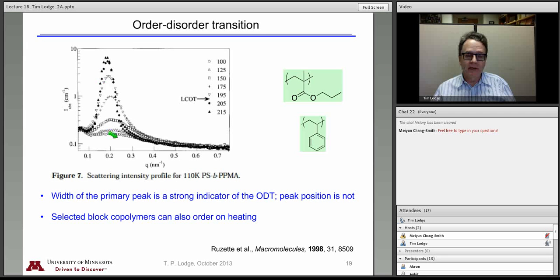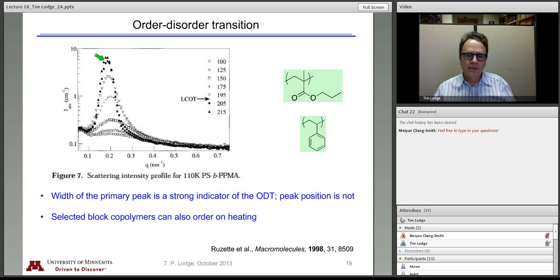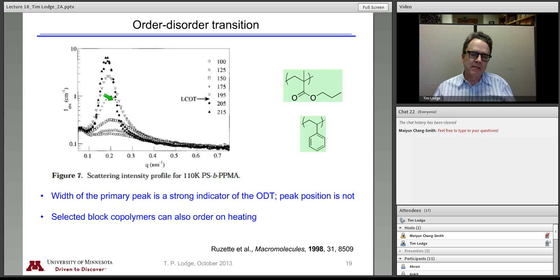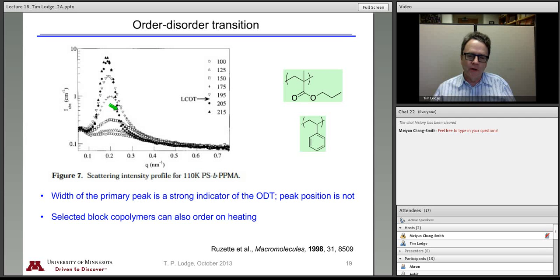The main point I want to bring out here is that if you just look at the peak intensity, you wouldn't necessarily know that dark points correspond to ordered states and open points correspond to disordered states. But what you can see is that the half width at half maximum undergoes a discontinuous drop between order and disorder. The dark points have a full width at half max that is distinctly smaller — a distinctly sharper peak — than the disordered state. If you have long range order, the Bragg peak will always be narrower than if it's a relatively disordered periodic structure.